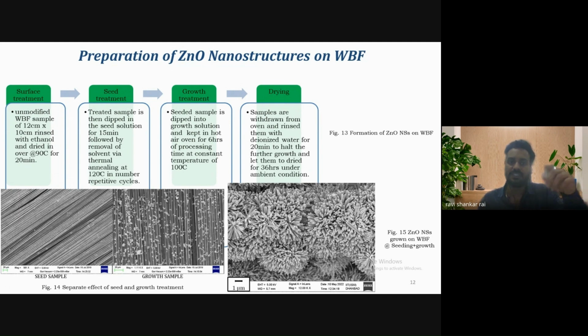After that, this seeded sample is directly dipped inside the growth solution, packed completely, and kept inside the hot air oven at 100 degrees Celsius for 6 hours. After this growth treatment, the sample is withdrawn from the oven and rinsed with deionized water to halt further growth of the nanostructure, and dried in ambient condition for 36 hours.